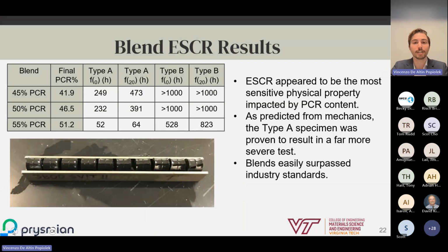Next, as ESCR was deemed to be one of the more important and critical properties, more testing was performed after the end of the semester. Testing was performed on both the Type A, more strenuous, and the Type B, less strenuous tabs, with the Type B being what it would actually be compared to for industry standards. As we can see, no matter which set of results you look at, we were able to pass the 48-hour threshold for all of our tests.